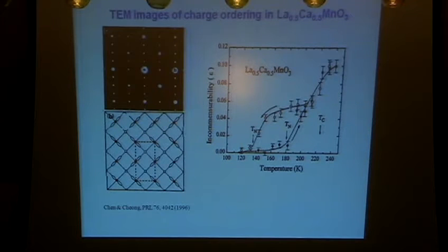So let's go looking for it. And of course, I already showed you a cartoon. Here now is a TEM image of precisely this doping, taken a long time ago, 1996. And the image you can see here, because you have that period doubling in here, you expect to see some extra diffraction spots. Here they are, there's one there, one there, one there.